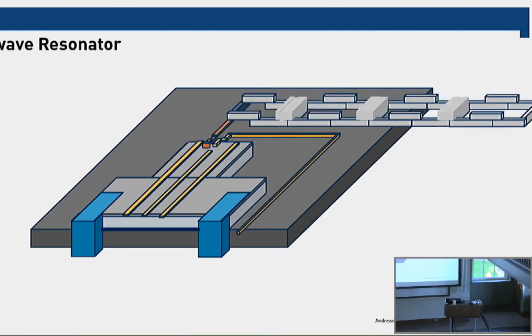and then we couple that to a superconducting resonator. And here you already see a more sophisticated version that we've developed for reaching the strong coupling limit. We've done experiments some time ago where this resonator was just a regular coplanar waveguide resonator with 50 ohm impedance. And while we were approaching the strong coupling limit, we thought, okay, how could we get another factor of 5 or so in our coupling strength? We did that by going away from 50 ohm impedance resonators to resonators with much higher impedance.